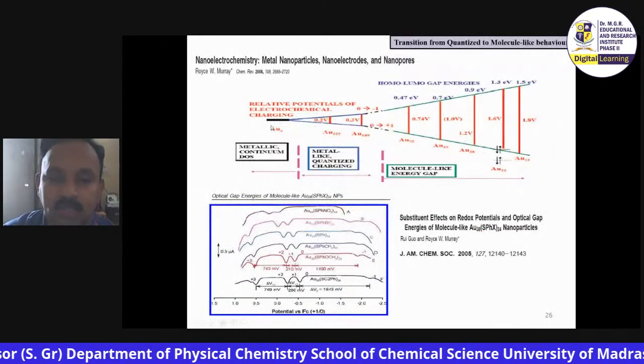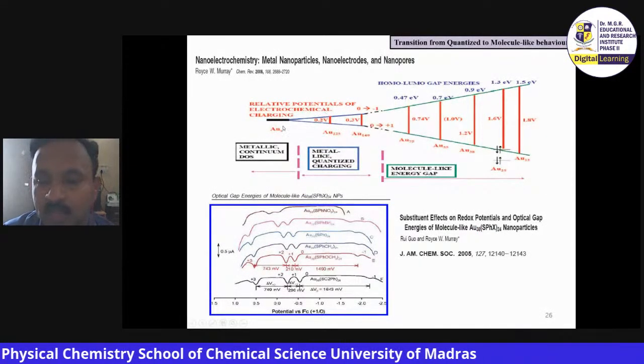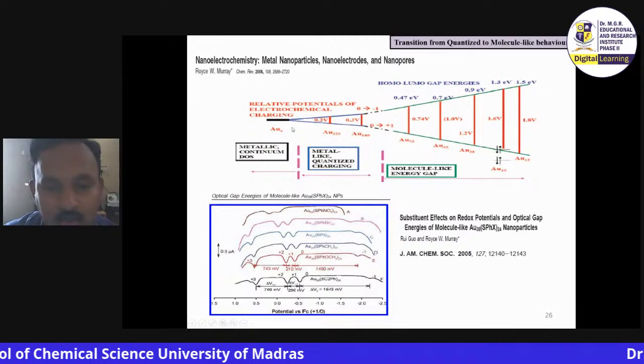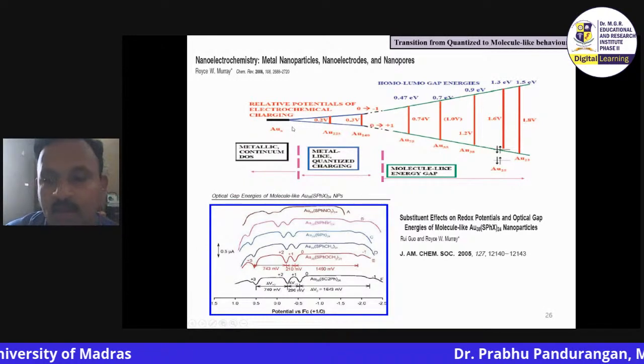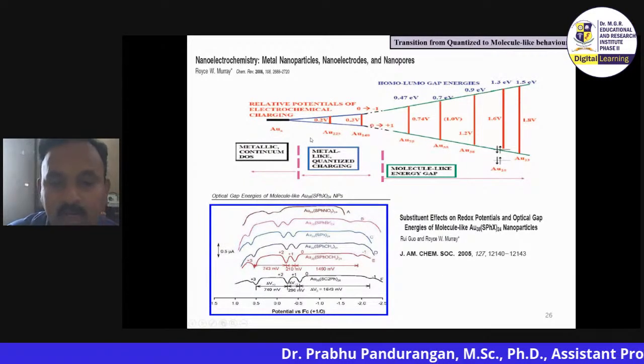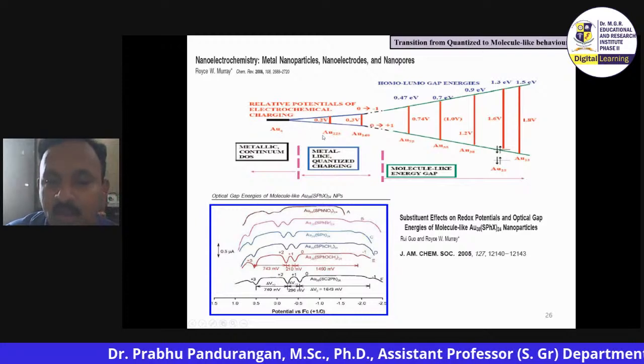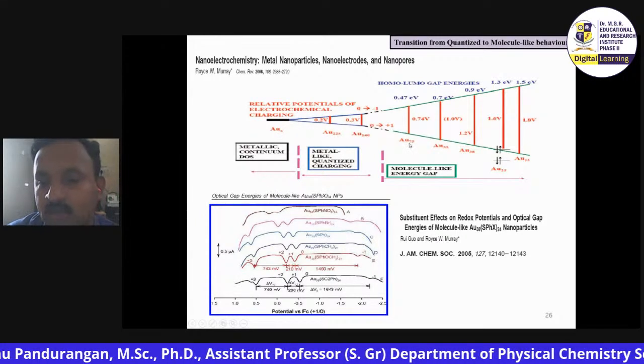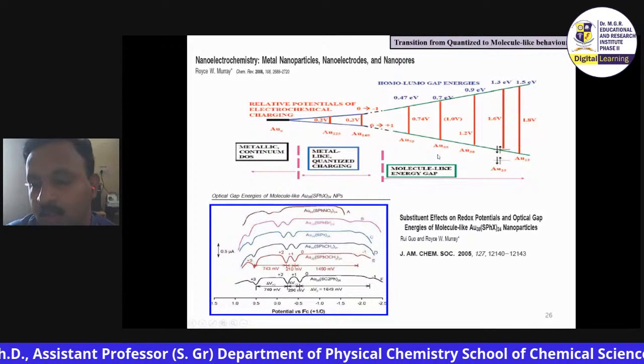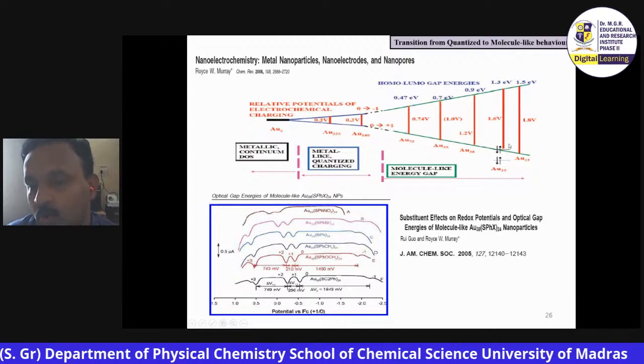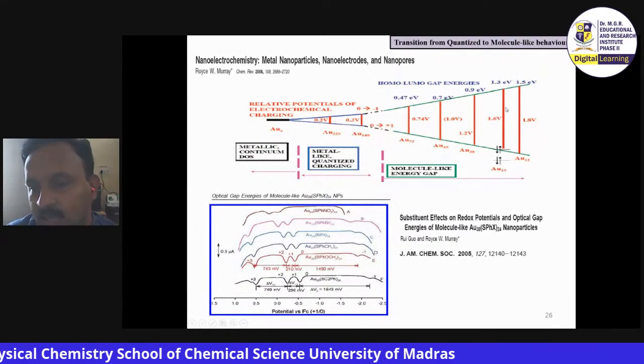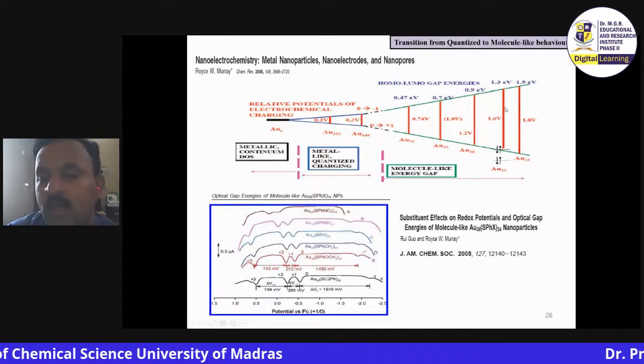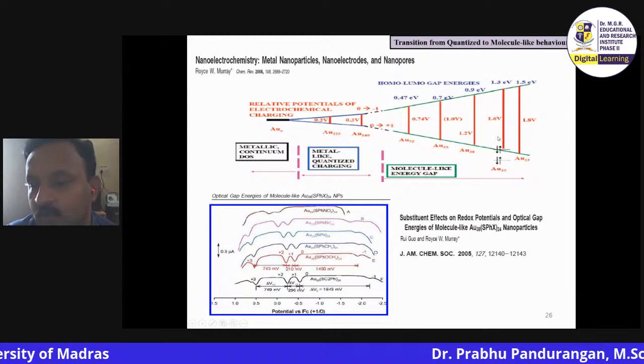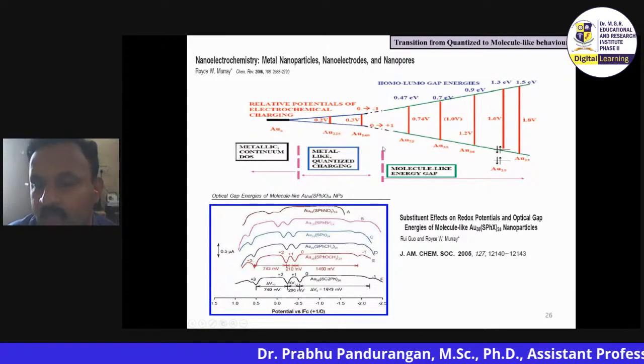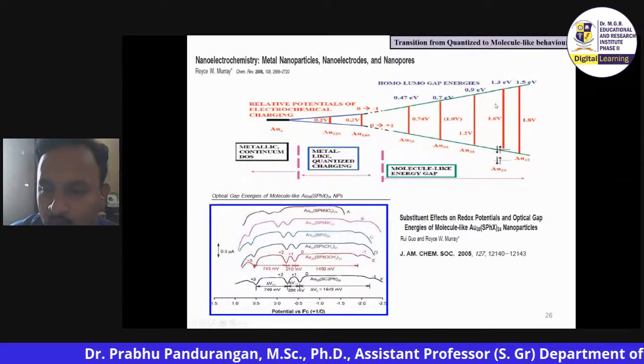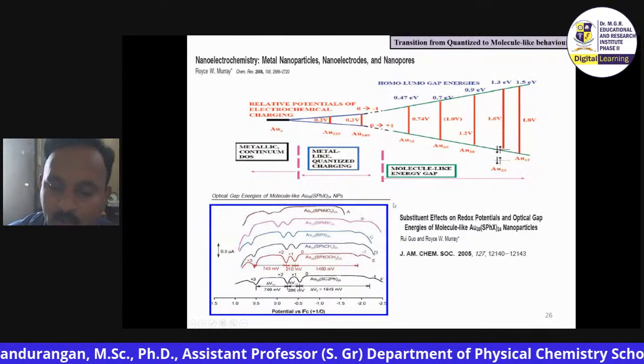I'll tell you that here you can see the relative potential difference against the number of atoms present. You can see this is a bulk. What do you mean by bulk? Even 1.5 is a bulk for gold 25. Even 2 nanometer is a bulk. So you start from here. You can see gold 225, 144, 75. They have quantified it with the help of mass spectrometry. And 38. Now 25. You can see the HOMO-LUMO gap. What is the HOMO-LUMO gap? This will decide the electronic transition both in photochemistry as well as in electrochemistry, where the gap is around 1.3 electron volt. So as the number of atoms decreases, this HOMO-LUMO gap widens, and this HOMO-LUMO gap will decide the electrochemical behavior of gold.